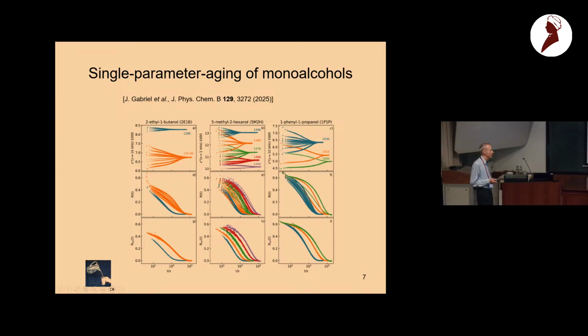More recent experiments, I won't go into great detail, but monoalcohols tend to behave differently from the ordinary van der Waals liquids which we usually study. So we wanted to see whether single parameter aging also works for monoalcohols, and the answer is yes. Here are jumps to two final temperatures, and many different jumps. What we did in this case was take the nonlinear one and predict the linear response from that, which should be unique. This collapse shows the predicted linear response at the different final temperatures. They collapse pretty well, again confirming this approach.